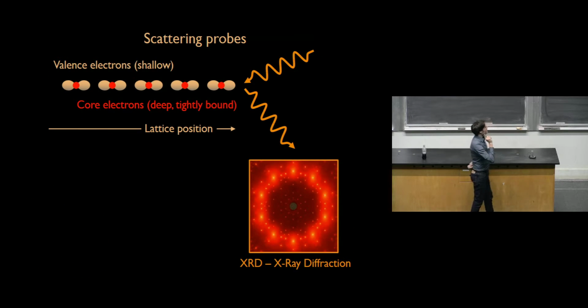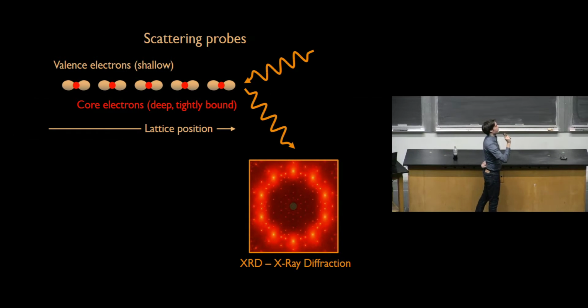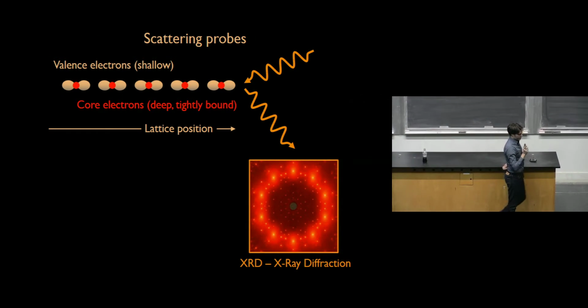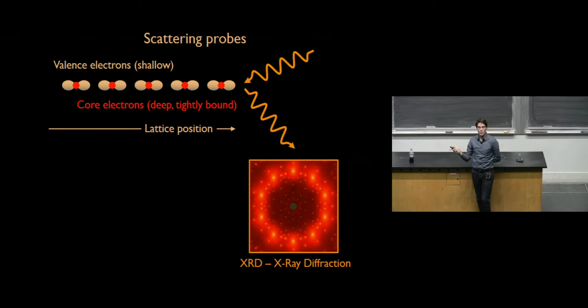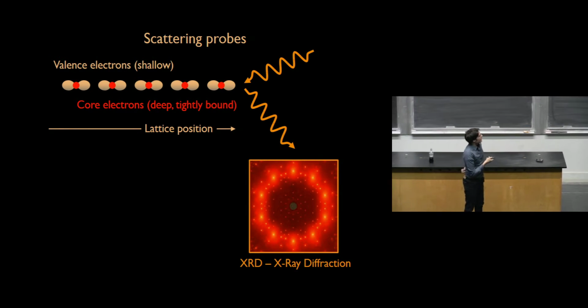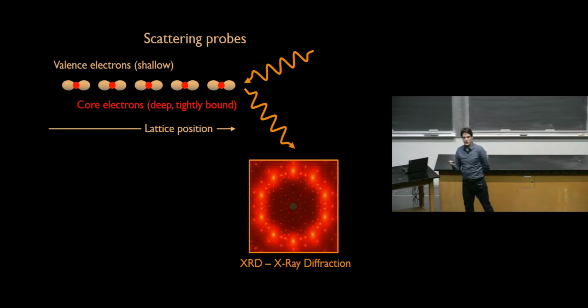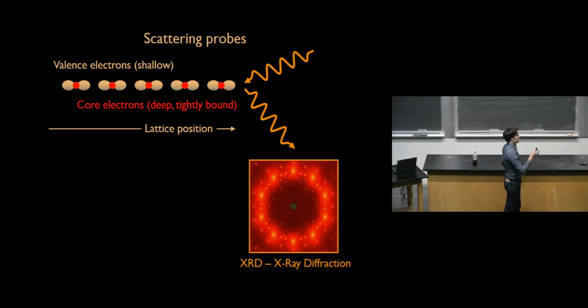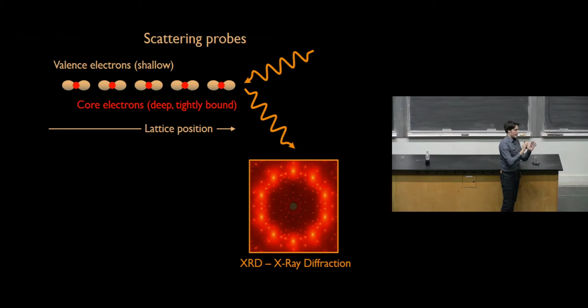There is only one problem. Typically, when you do X-ray diffraction, which is scattering using short wavelength photons, which are X-rays, you measure the lattice. And why is that? Well, that's not because the photons interact with the atoms. The photons actually always interact with the electrons. But an atom has a certain number of electrons surrounding it, and most of those electrons are core electrons. There are only a few valence electrons, which are the electrons that are close to the Fermi level in your material.